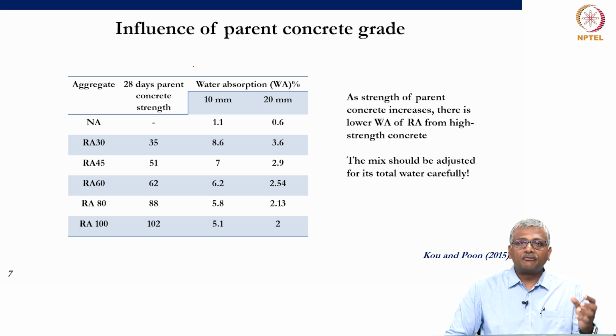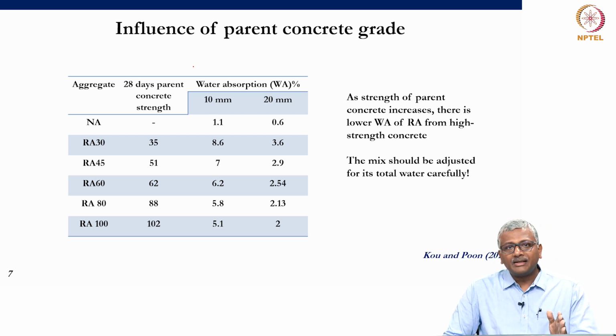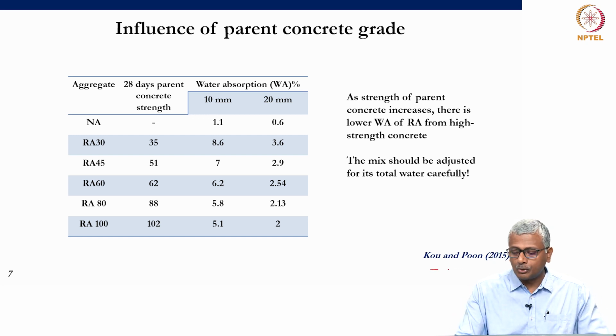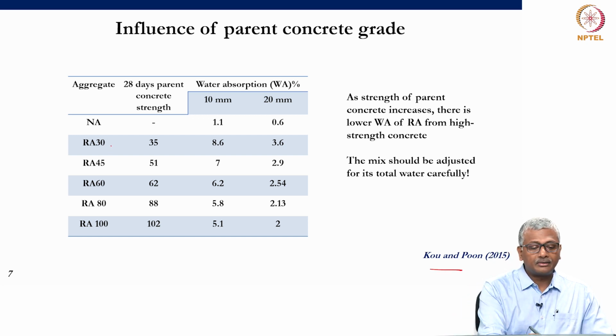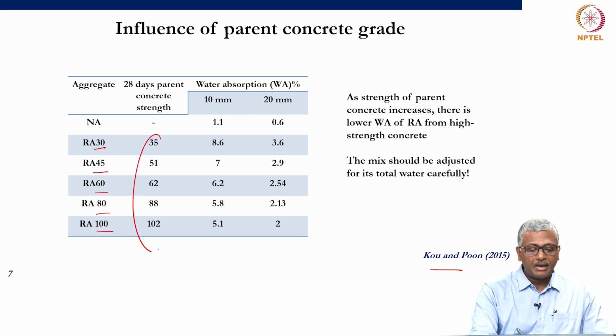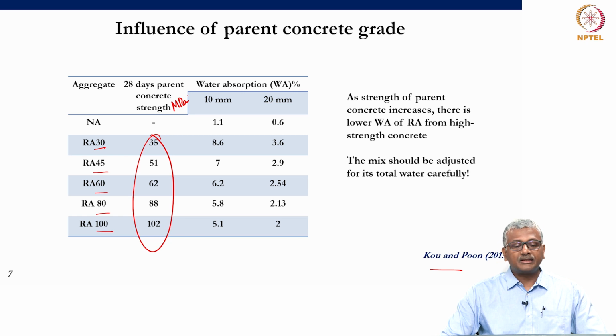Because of this, when you actually prepare recycled concrete aggregate from different grades of concrete, there will be a difference in water absorption levels. For instance, in this study by Kou and Poon, they prepared recycled coarse aggregates from 30 MPa, 45, 60, 80 and 100 MPa concrete. These are the parent concrete strengths in megapascals at 28 days. So, you can see that the strengths vary from 35 to 100 megapascals.